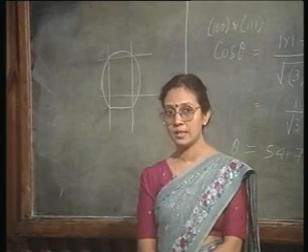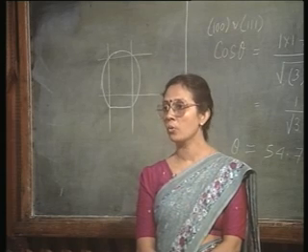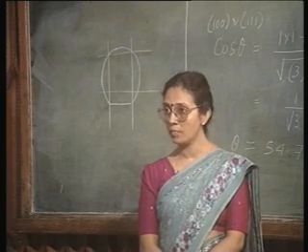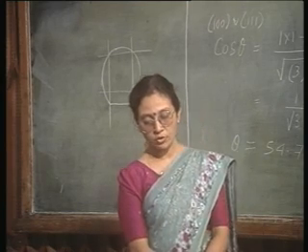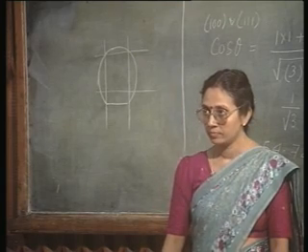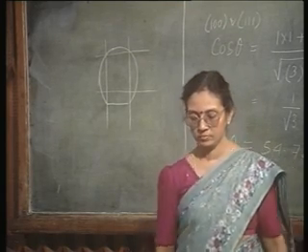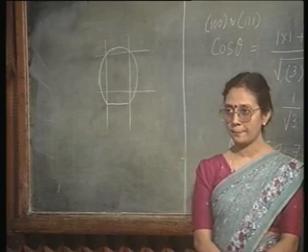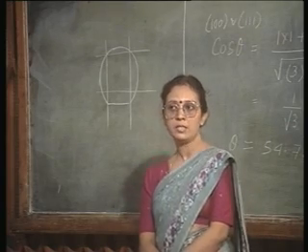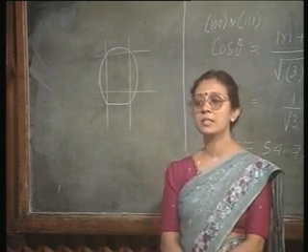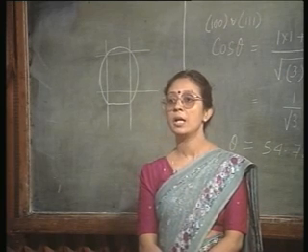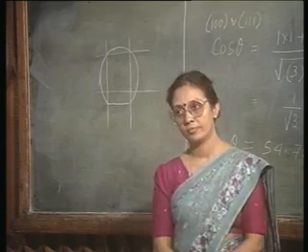All the 4 lines that I have drawn are the 4 1 1 0 directions which are meeting in mutually perpendicular direction, and therefore, we can easily cut rectangular chips. Okay. Why did I say that this is an advantage of 1 0 0 wafer? Simply because this advantage does not exist if I have, for example, an 1 1 1 wafer.